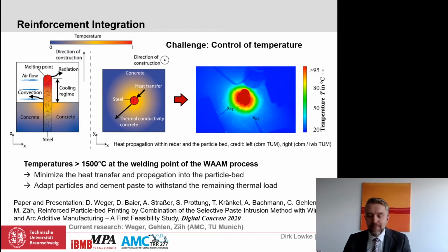The temperature at the welding point exceeds 1,500 degrees Celsius. However, as you can see in the picture on the right side, preliminary tests show that by moving the weld point out of the particle plane by only 25 millimeters, the temperature load in the particle bed can be reduced to around 100 degrees Celsius without any further active or passive cooling strategies. So if you're interested in this special technique, then I refer to the presentation of Daniel Vega on Thursday in room D.